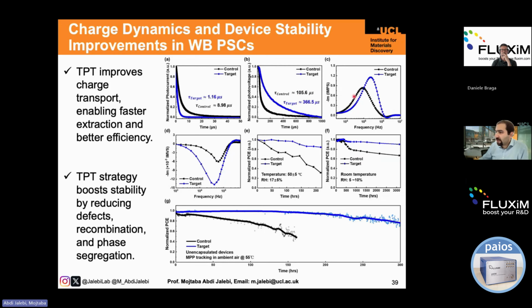And this is IMVS and IMPS. As you can see, better performance for the target sample in both cases. That shows, again, overall, we have a reduced density of traps. And also we have better charge collection efficiency in both interfaces, for electrons and also for holes.